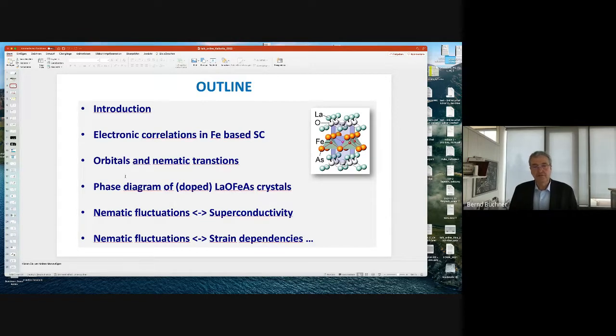And then I will move to recent results, connected to the fact that we were now able, after a long time, to grow large crystals of these 1111, or lanthanum oxygen iron arsenide, crystals. And we have revisited this phase diagram. We address the question of whether there are connections between nematic fluctuations and superconductivity, and I will show you that the normal state is also very, very strange.